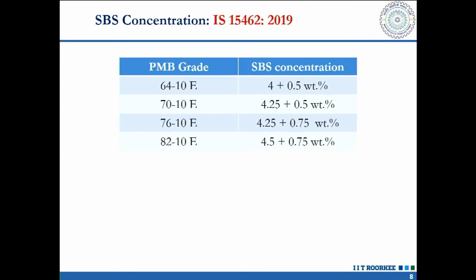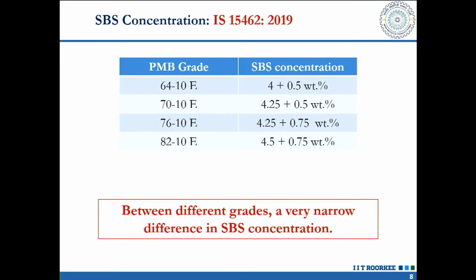The second study is fatigue life with respect to polymer content. So 4-point bending beam testing was carried out, and we can see from this that almost a 5 times decrease in the fatigue life is observed when you go for a polymer concentration of 4.5 to 7%. So this SBS concentration is indicative for our PMB grades, for different loads like extreme loads. 4 to 4.5% is the ideal weight percentage range for different PMB grades. So this range is highly effective for different grades, with very narrow differences in SBS concentration.